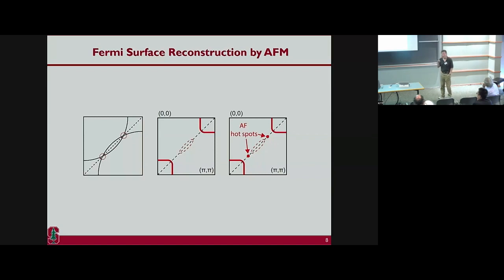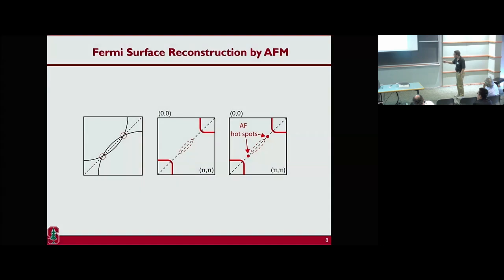That's what will be the expectation. Okay. What I'm going to tell you is that no, the superconductivity actually has a maximum of the superconducting gap at the so-called hot spot, meaning where the original Fermi surface crosses the antiferromagnetic zone boundary. Okay, that's where the maximum is. In fact, it's not on the reconstructed Fermi surface. That's the takeaway I'm hoping to make a case for you.